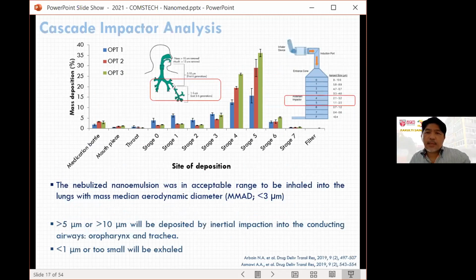Now we can see that using the cascade impactor analysis, the formulation can go basically to stage 4 and 5, and some also deposited in stage 6. If you look at it, it's actually around here down to here, alveolar and alveoli. It is very important as well. If it is more than 5 or even maybe 10, it will deposit in the inertial impaction, which is more towards this area.